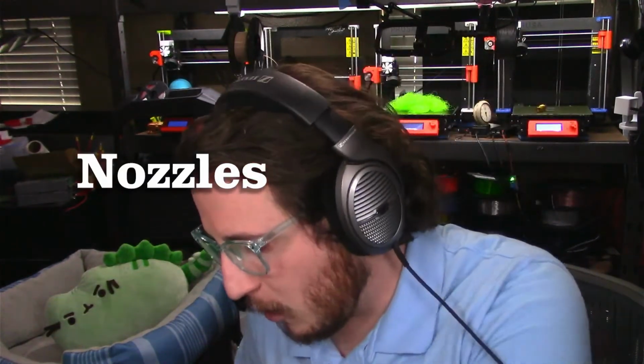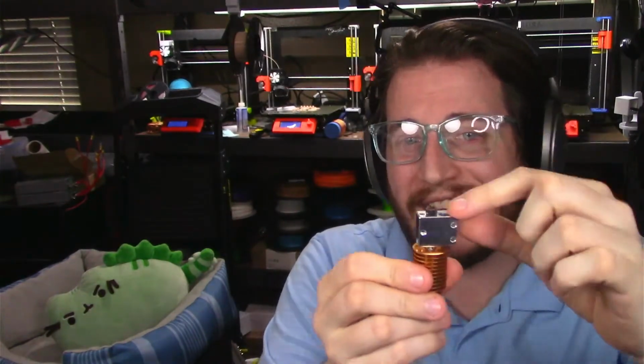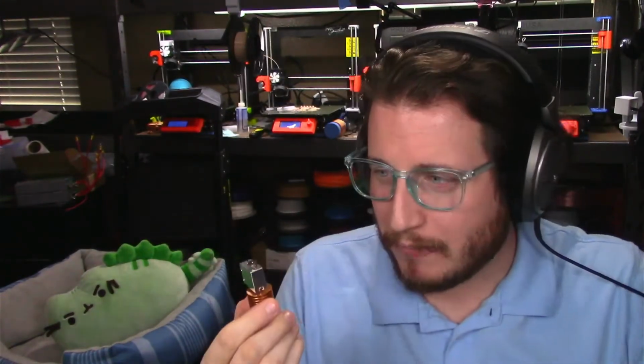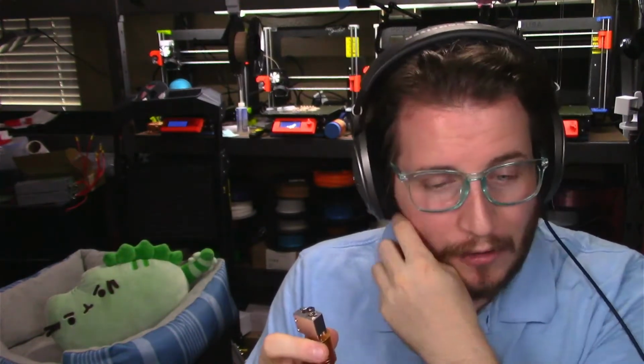And the nozzles are important. Nozzles kind of let you know what you can and can't print with. This is a tungsten carbide nozzle. And that means that we can print basically everything because tungsten carbide is the paragon of metals. Normal 3D printers come with brass nozzles, and those nozzles are great for your everyday materials like PLA, PETG, ABS, ASA, all the general materials that we mentioned in the beginning of our materials FDM video, but it cannot do any of the filled materials like carbon fiber, glow in the dark, wood fill, that have a tendency to wear out the nozzles because those materials are harder than brass. Yes, even wood fill is harder than brass. Brass nozzles are consumable. Nozzles in general are considered consumable in the 3D printing industry. Keep spares, they're not expensive.